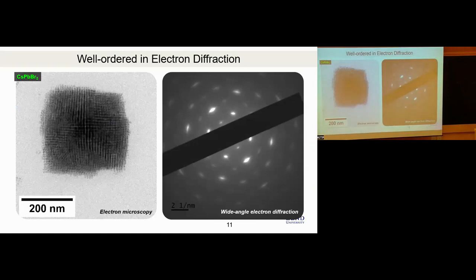So now we looked at the smaller superlattices in electron microscope. So here's one example of this smaller superlattice in TEM, and we recorded wide-angle electron diffraction, and noticed something remarkable: typically you would expect to see arcs, but we saw very, very narrow arcs, practically spots, indicating very high crystallinity of the superlattices. Well, that means single crystal, no? Yes, so it means essentially that each cube inside of this supercube is aligned with respect to each other quite precisely.